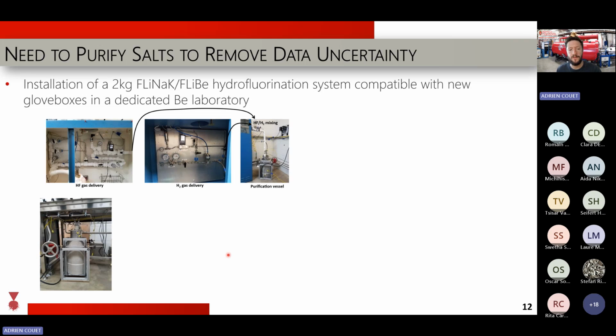First of all, if you put HF in there, all the oxide particles in your salt are going to be fluorinated, right? The oxides are going to decompose to fluoride. And then it's a question of reducing those fluorides. So you bubble H2 to reduce those fluorides to metal, and then you just have to sieve the salt to remove those metal particles, which have very low solubility in the salt. So that works pretty well.